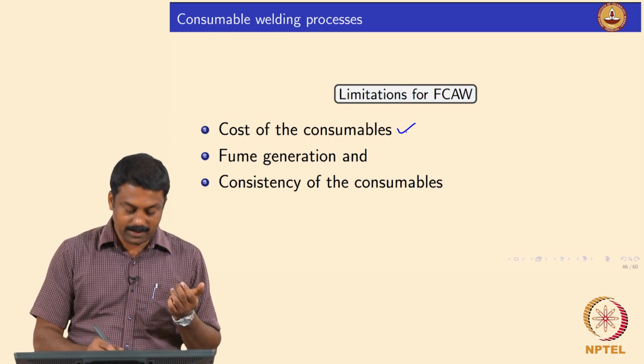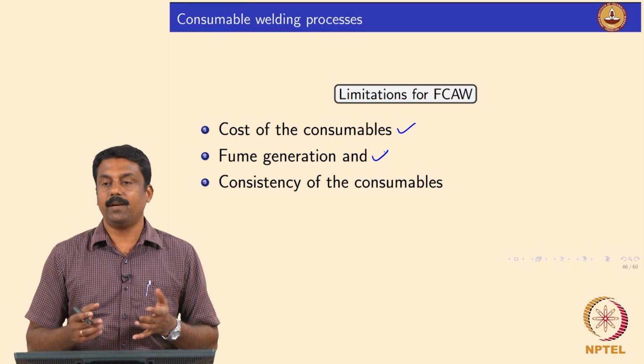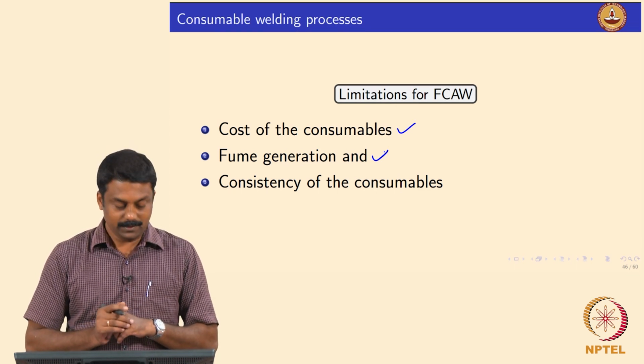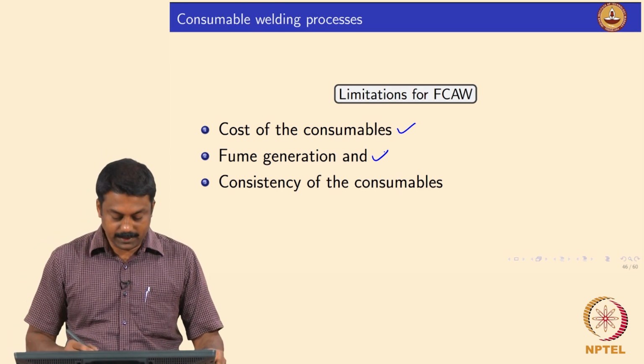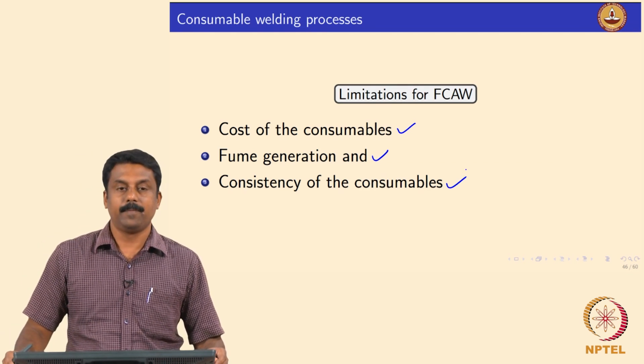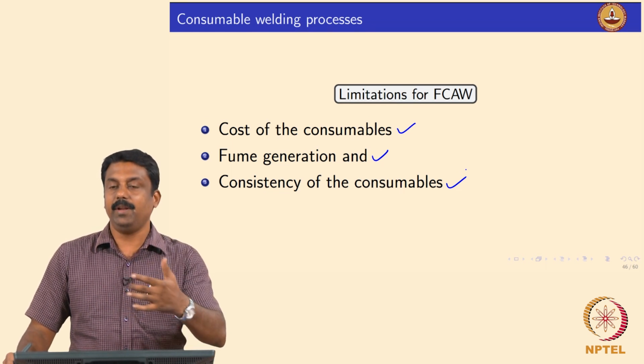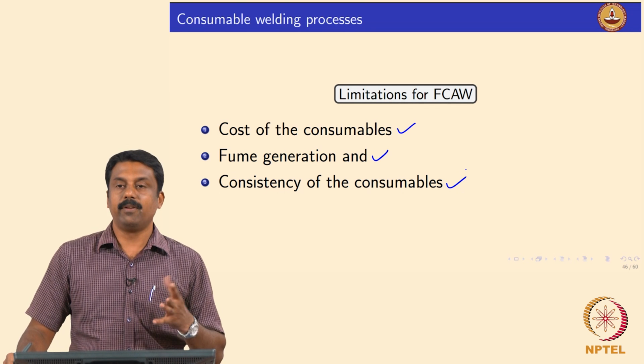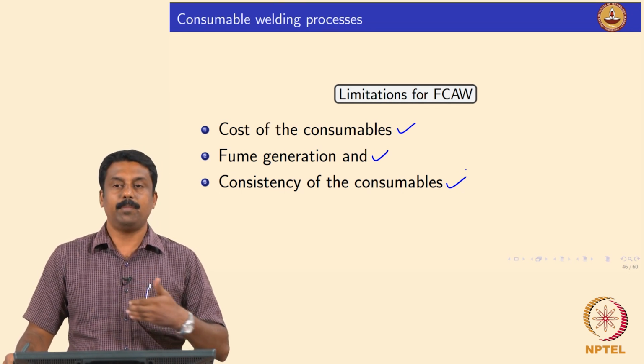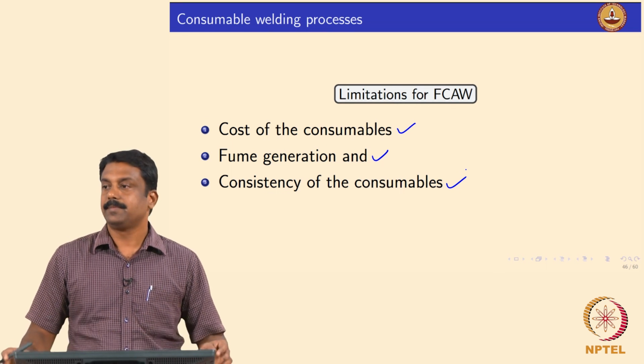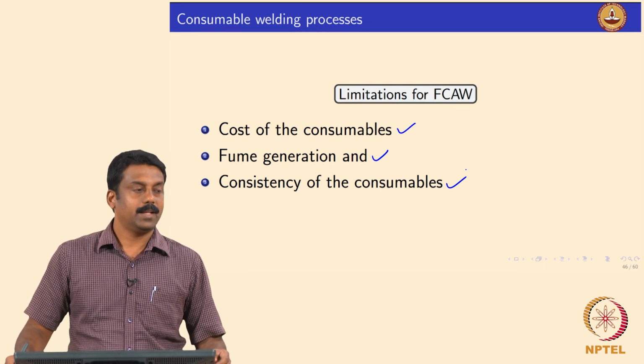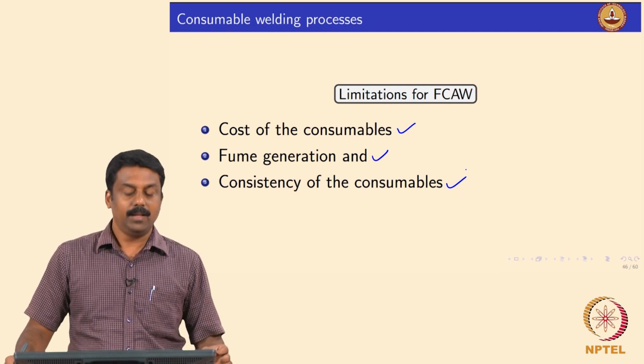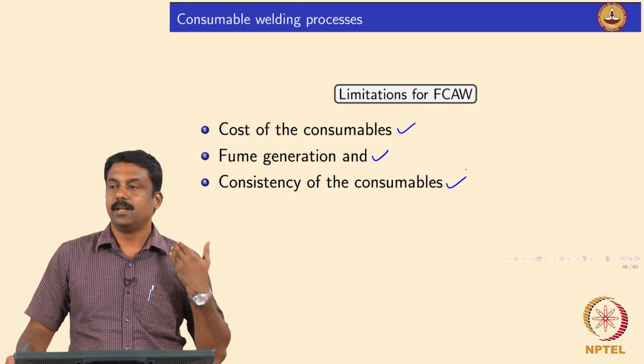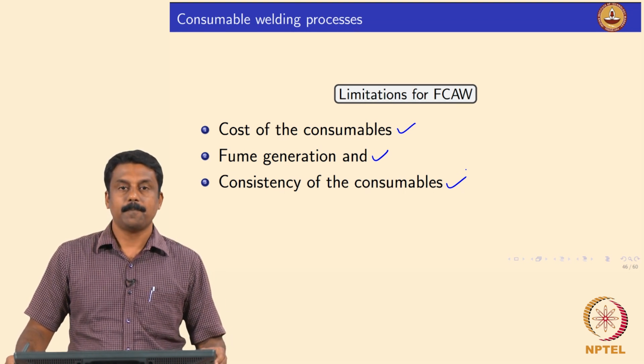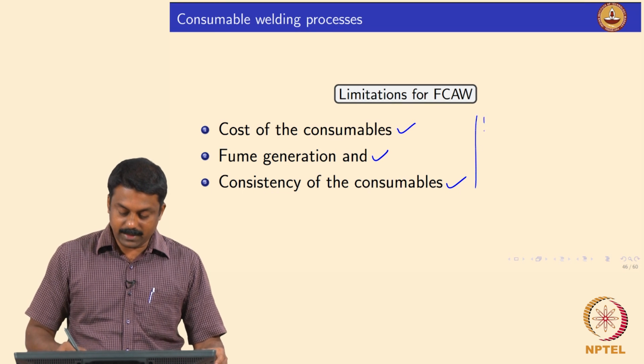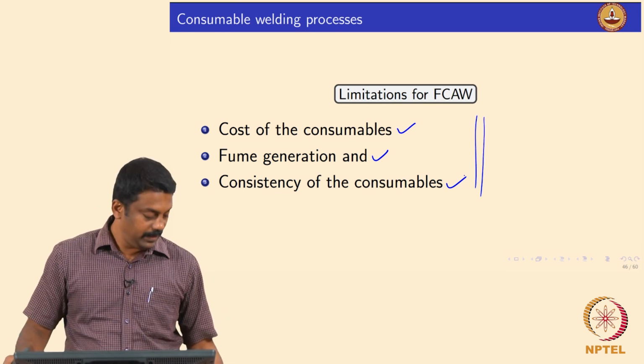right. And the other important disadvantage is fume generation by the burning of the fluxes and then ferroalloys you have in flux, and then consistency of the consumables, that is also problematic because achieving a uniform flux coating is also very tricky. These are powder based, you will have to mix it with binder and then deposit. You need to achieve a homogeneous mixing of the fluxes, the ingredients in the fluxes. So you always have some difference in consistency across the length of the electrodes, right. So these are some disadvantages, but this can be overcome by the advantages of the process.